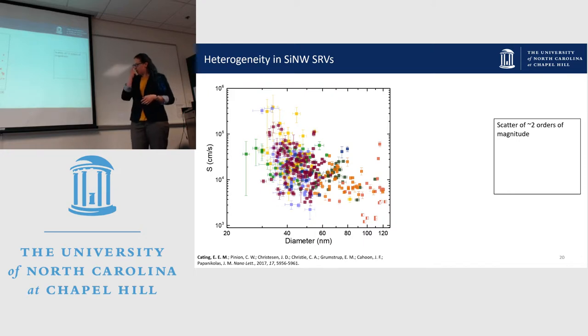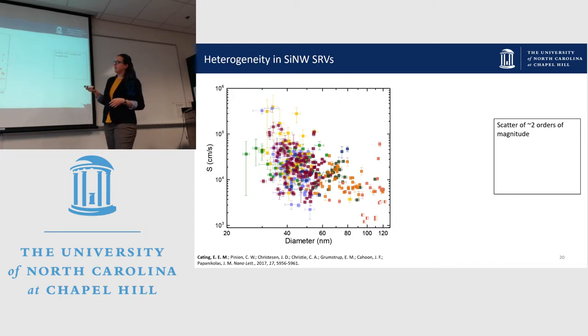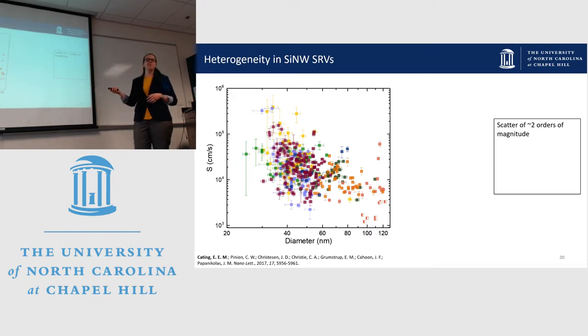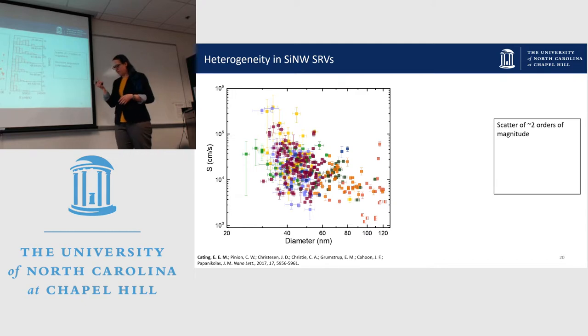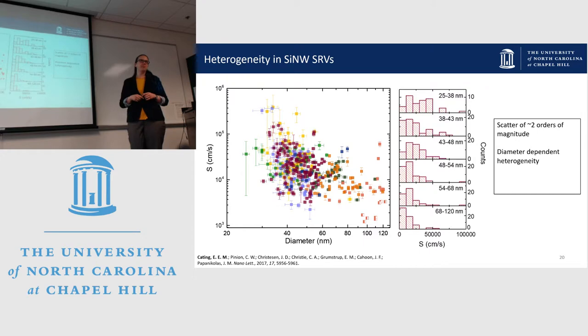The second thing I want to point out is it looks like the scatter is larger in smaller wires. And so I histogrammed these. So you can see that the distribution of surface qualities is a lot larger in wires that are under about 40 nanometers than it is in wires that are, say, above about 70 nanometers. Right? So this means that smaller wires have surfaces which are less consistent than the larger wires.